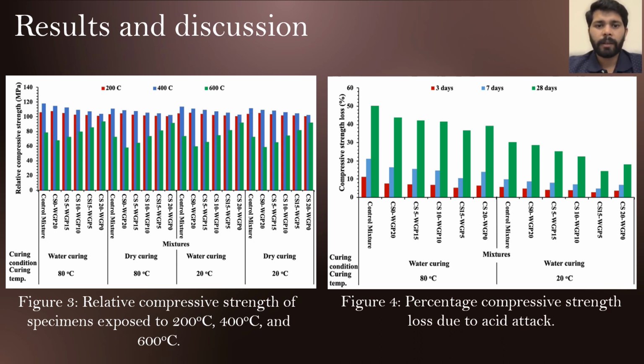Figure 4 presents the percentage compressive strength loss due to acid attack. The compressive strength loss was found more at higher temperature than ambient temperature. Compressive strength loss due to acid attack was found maximum in control mix, while Cenosphere incorporation reduced the compressive strength loss, which can be due to the increased packing density by filling the voids, which prevents the ingress of acid. The second reason could be because of pozzolanic reaction induced by Cenosphere, which fills the pores with hydration gel and prevents the acid penetration.